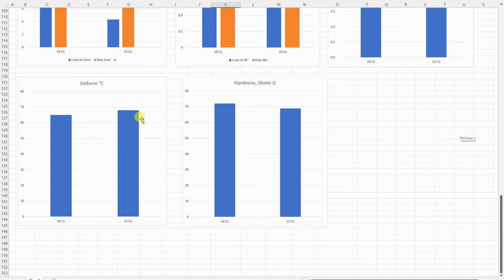The deformation temperature, here again the PCTG was better, but the difference was maybe 3 or 4 degrees Celsius only. And this is the last measurement, the hardness, which, yes, the PETG was harder in this case, but I'm not really sure should I measure this in future. Is the hardness important with the plastic?